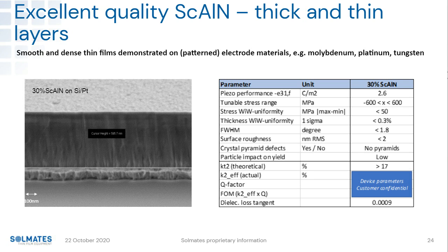Some people report half range, but we report full range. Thickness uniformity, everybody knows it needs to be uniform because the thickness is the resonance frequency, and otherwise you head into cumbersome trimming. Rocking curves are good. Surface roughness, it's pretty smooth, as you can also see from the cross-section. Crystal pyramids, also called abnormal outgrowth, very important factor. We can do that. We can control the stress also for 40% and have means and ways to minimize the crystal outgrowth. So we claim pyramid-free deposition.